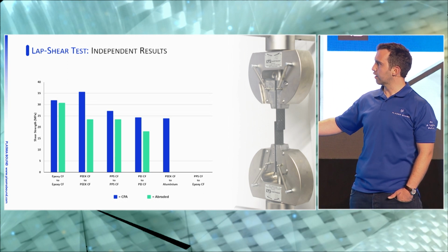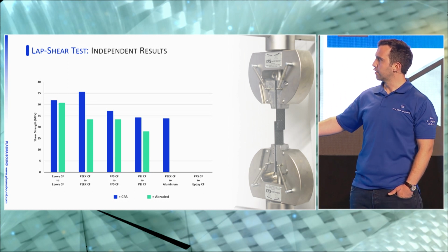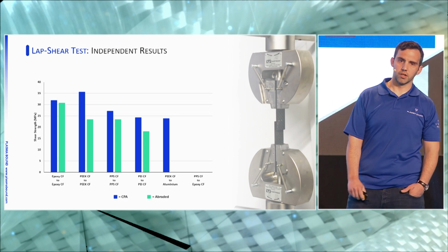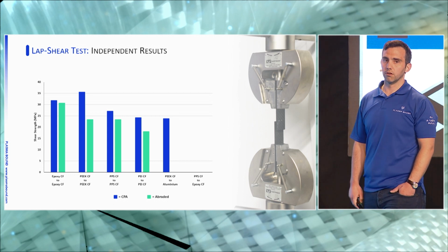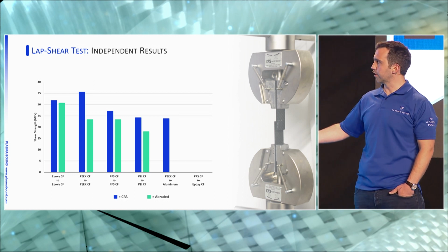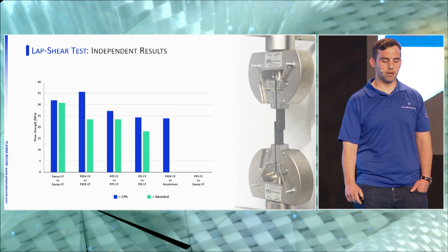But when it came to PEEK to aluminium, it was the first time that the failure occurred on the aluminium side. They'd never anodized the aluminium side during testing because they'd never had to see it cause a failure. It now failed on the aluminium side. The PEEK held longer than the aluminium.